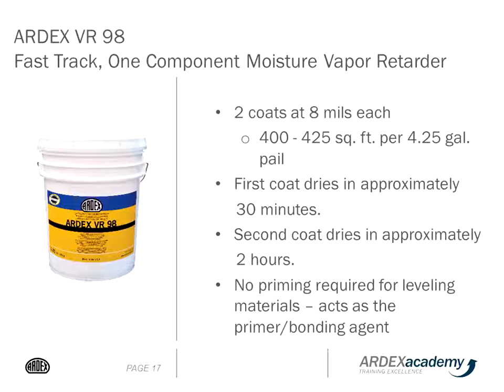From an application standpoint, it is a two-coat system. A 4¼ gallon pail will cover roughly about 400 to 425 square feet, both coats. Okay, the first coat dries relatively quickly, in about 30 minutes. You're obviously applying that over clean, porous concrete, so the concrete pulls in the moisture. It dries pretty quick. Second coat, roughly in about 2 hours.